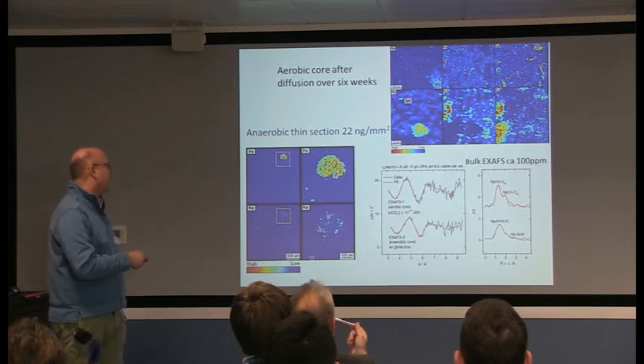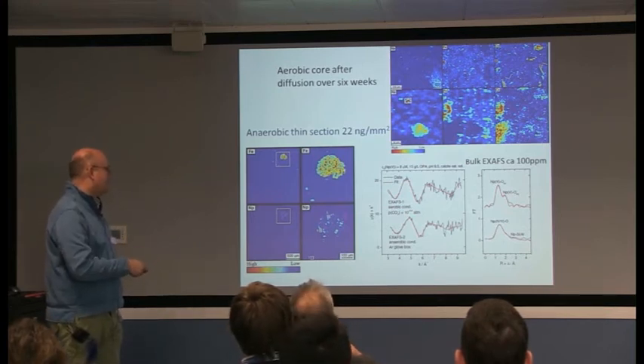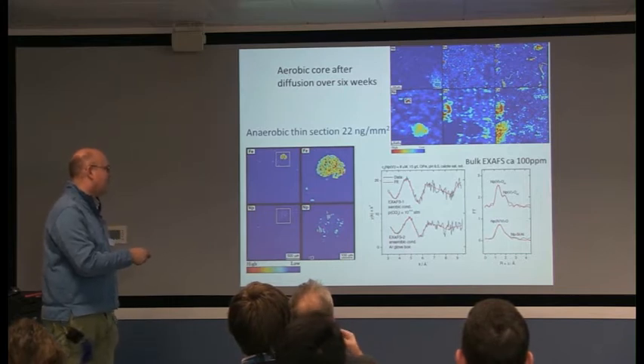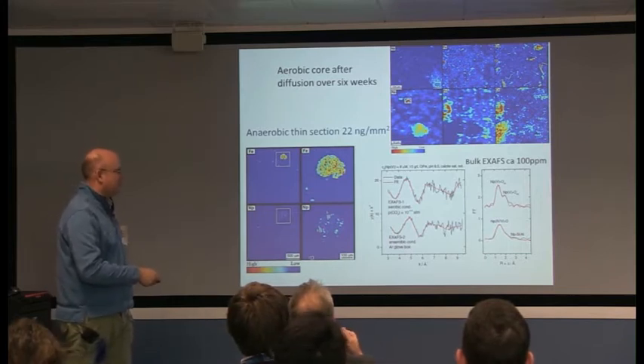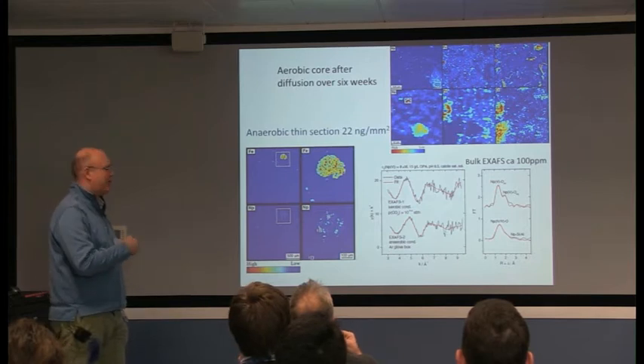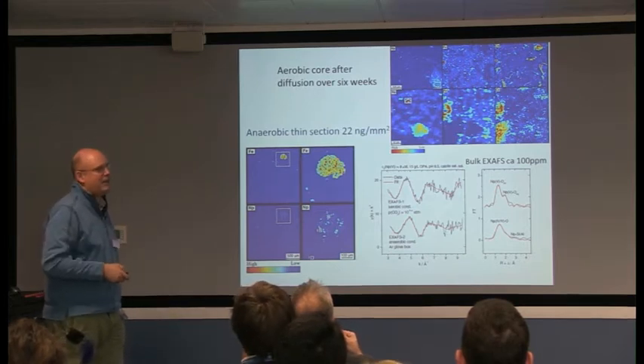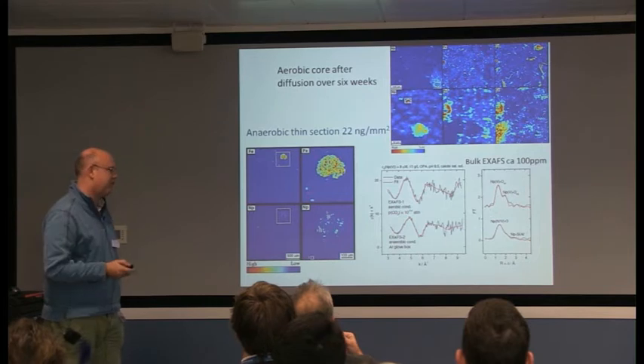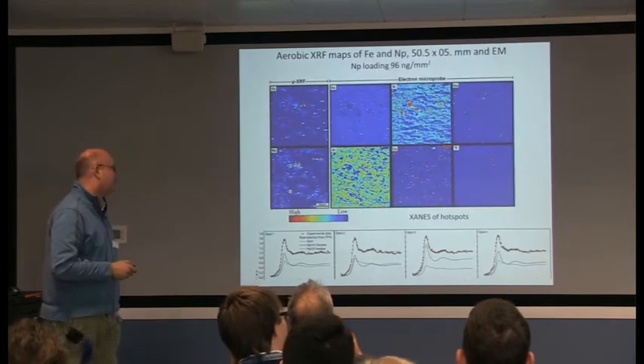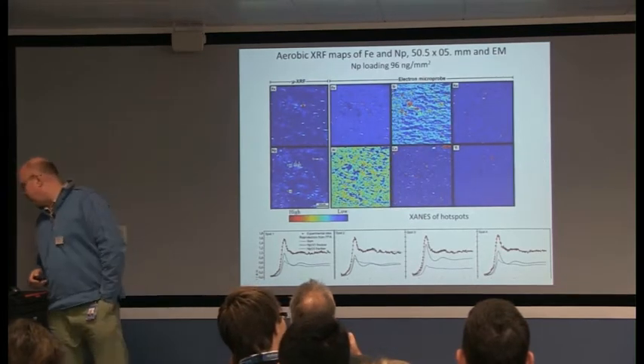If you look at the anaerobic section, the neptunium is strongly associated with this iron particle, and some of the neptunium is reduced to neptunium-4, showing that in anaerobic conditions the iron can reduce it. They also did diffraction on this and showed that pyrite was one of the things that helped reduce the neptunium.